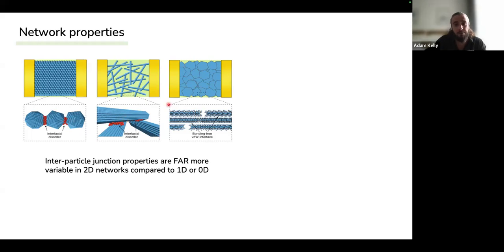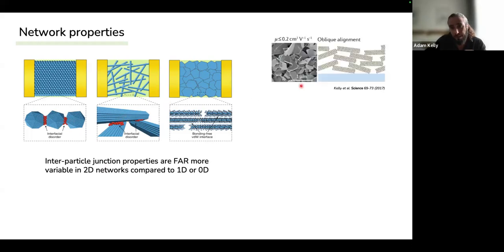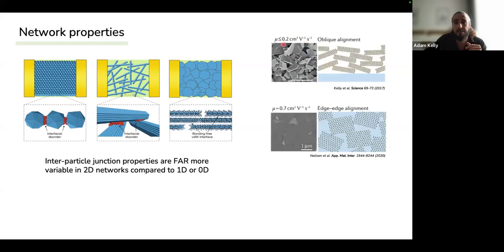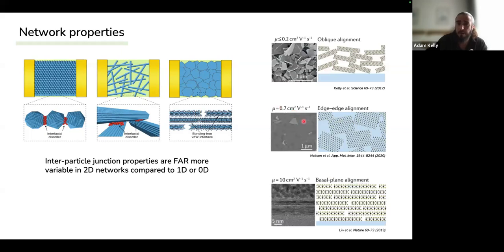But when we look at 2D material networks, what we find is that depending on the sizes of the nanosheets, we get this kind of oblique alignment, as we call it, where it's like all these rigid disks or rigid bodies in a jammed system. If you have something like this, the junctions between the sheets themselves tend to be quite small, so we end up with low network mobilities. If you use this liquid-liquid interface method, we can align all the nanosheets up edge to edge, and we get a slightly better mobility out of it. And then if you do something like spin coating, or you do this liquid-liquid deposition technique iteratively, you can align the nanosheets up like this, and we get much higher mobilities out of it.